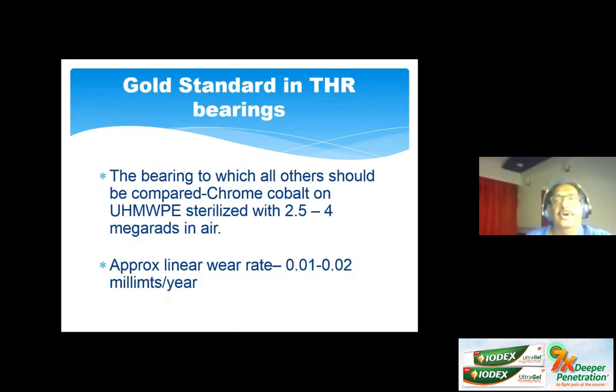The bearing to which all others should be compared would be the chromium cobalt on the ultra high molecular weight polyethylene, which is usually sterilized with 2.5 to 4 megarads in air, with a linear wear rate of about 0.01 to 0.02 millimeters per year. Now, this is a gold standard, and we try to see how the newer bearings compare to this. Now, this talk may have a little bit of tribological inputs, but we will try to keep it as minimum as possible. At the end, you will realize that it is more experience-based than evidence-based.